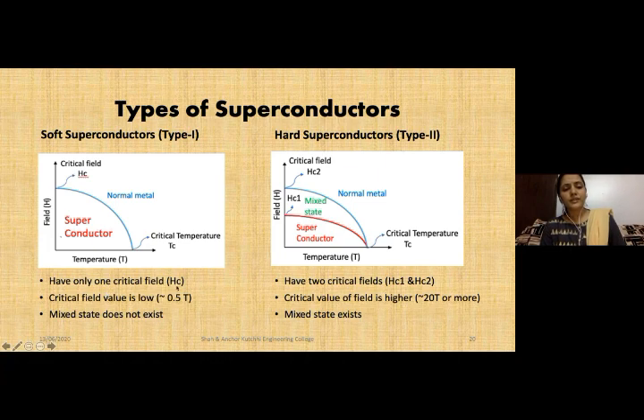You can see here they have only one critical field, and this critical field is very low, almost like, just to give one idea, I have written around 0.5 Tesla, and there is no mixed state. That means either the material will be superconductor or normal. There is nothing in between. But when we see type 2 superconductors, there are two critical fields, and for the material to become a normal metal, it has to go through a state called the mixed state. In the mixed state, the superconductivity starts getting lost, but it's completely lost only after we cross the critical field value 2, and then the material gets converted to a normal metal.